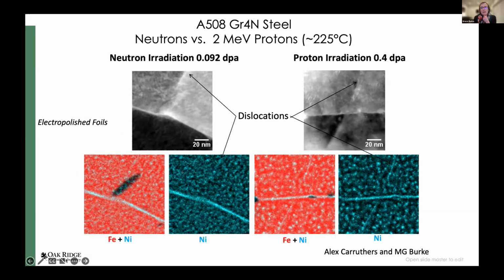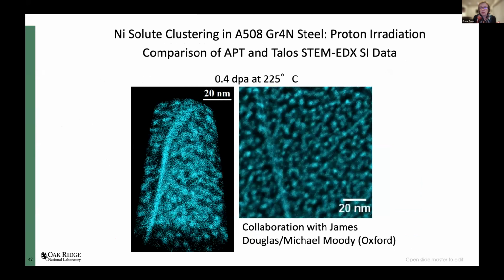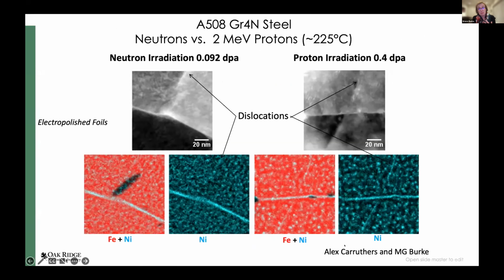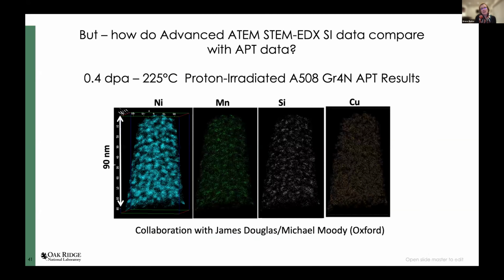So we can see that we're getting nickel clustering with neutrons. We're also getting it with protons, as well as nickel segregation to boundaries and dislocations. We'll notice that the scale bar here now is 20 nanometers, so these are actually quite fine. And electron diffraction did not show precipitates. This was the work of my student, Alex Carruthers, well now Dr. Carruthers. And how would this compare with atom probe tomography data?